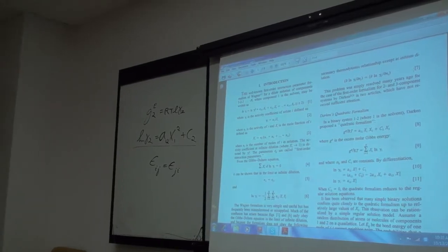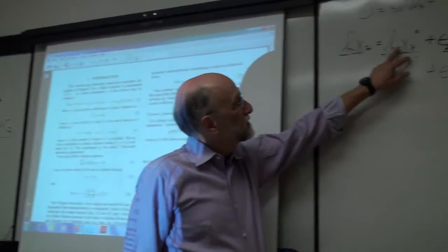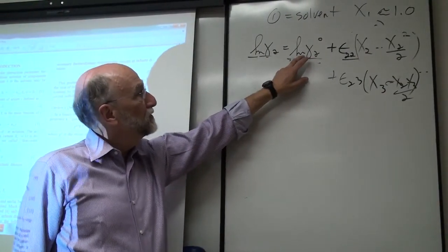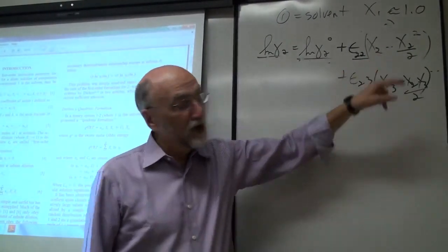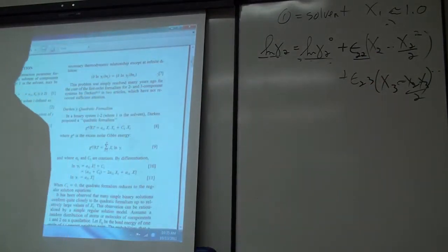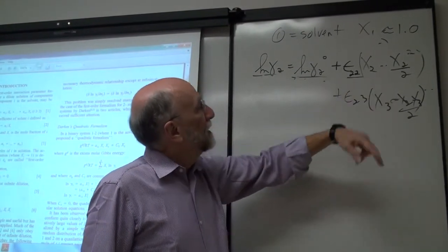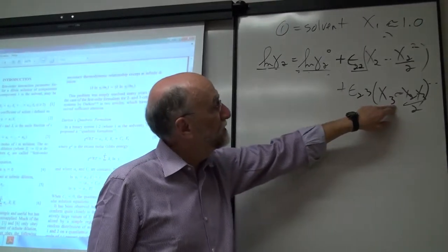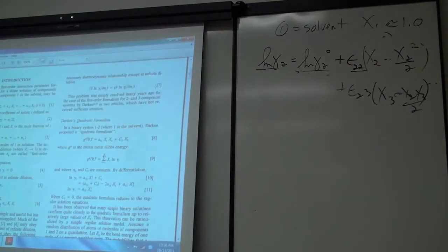Alright, so that's Darken's interaction parameter formalism. But you see, the interest is in the physical meaning. The first term, log gamma Henry, is what happens at infinite dilution, and it's constant, because when you take a huge amount of component 1 and put atoms of 2 in, every atom of 2 goes into the same environment, so every atom of 2 has the same energy increment, and you get a constant. If you start getting more and more component 2, then there's a probability that the atom you enter might find itself next to another atom 2. In that case, there's going to be an interaction energy, epsilon 2-2, x2. Or it could find itself next to an atom 3, epsilon 2-3, x3. This gives you a problem, but if you look at it in the Darken formalism way with the extra term, you're all set.